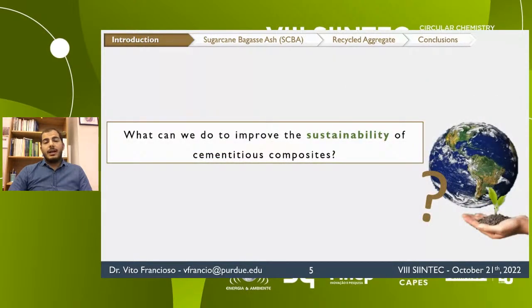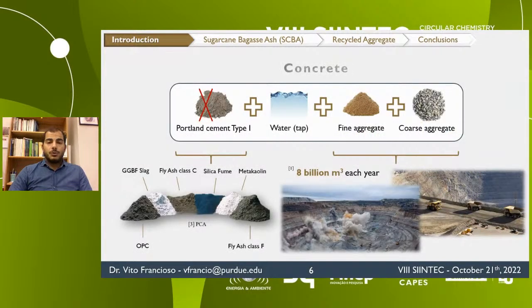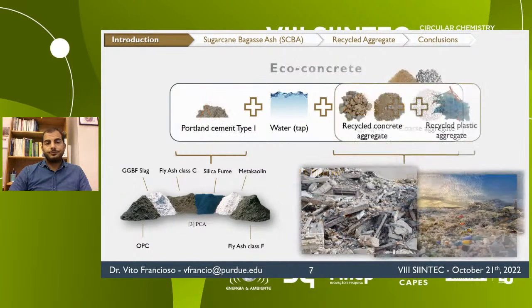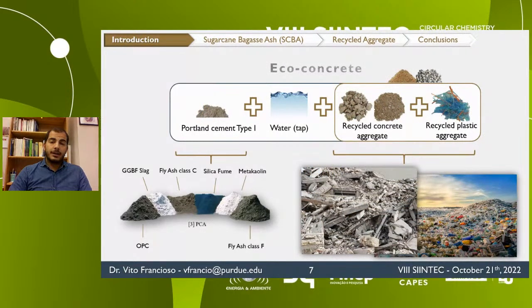Now, there are different approaches to reduce the environmental impact of cementitious materials. One approach is reducing the cement content, for instance, substituting it with supplementary cementitious materials. SCMs are natural materials or industry byproducts used as admixtures in concrete to make up part of the cementitious component. Another approach is replacing natural aggregate with recycled aggregates, such as recycled concrete aggregate and recycled plastic, which can contribute to reducing both the natural abiotic depletion and waste generation.